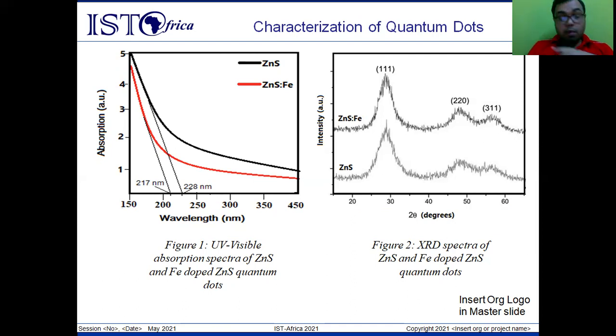So in normal, that is undoped zinc sulfide, the absorption is at 228 nanometer, while for doped zinc sulfide quantum dot, it is a bit blue shifted. This little blue shift is due to increased nucleation rate on addition of dopant ions. This has been observed previously also in other related works. So the absorption range starts from around 200 nanometer. That is, it is actually the UV region.